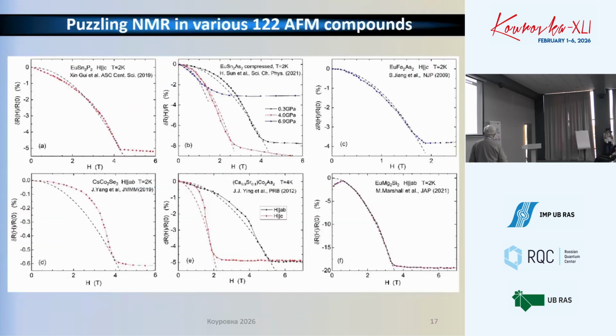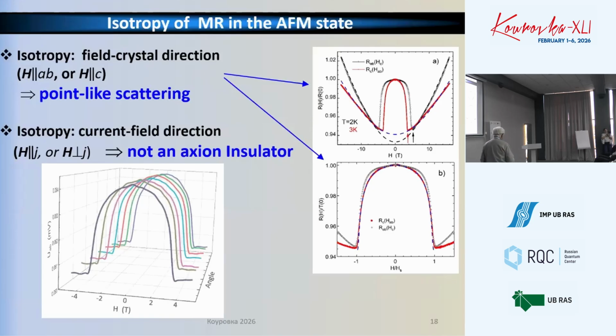Now, what I said in the beginning, that this magnetic resistance is tiny, but it's intrinsic to the whole class of materials. I don't show the whole class, but just 6 various materials show similar parabolic type magnetic resistance, which in some materials is about 6%, and in some other it's 20%. It's small. All of them are layered antiferromagnetic materials.